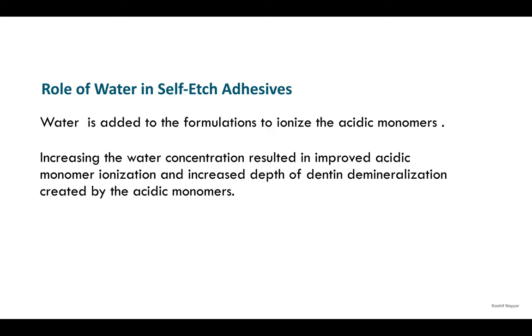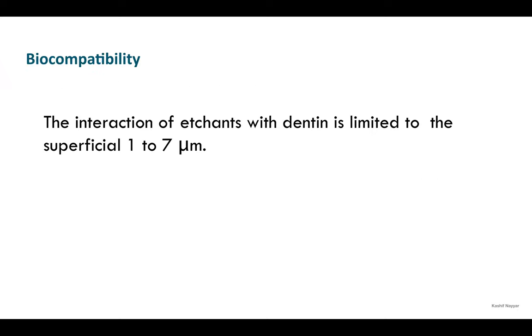So what is the role of water in self-etch adhesive? Water is added to the formulation to ionize the acidic monomer, so they can better penetrate inside the collagen network. And increasing the water concentration resulted in improved acidic monomer ionization and increased depth of dentine demineralization created by the acidic monomer, because they can penetrate better. Regarding the biocompatibility, the interaction of the etchants with the dentine is limited to the superficial area only, 1 to 7 microns, no more than that.